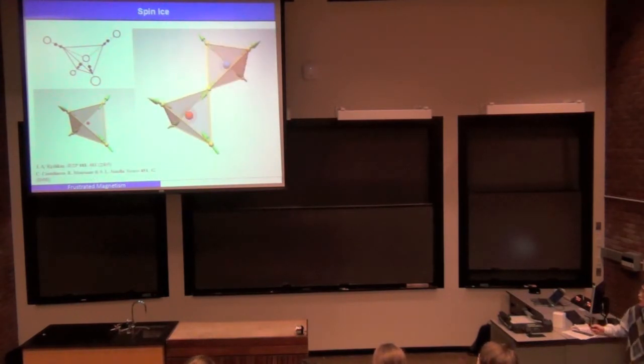And later people realized that when you have these so-called ice rules to enforce the two-in, two-out structure, if you flip a single spin out of the ground state, for example, if we flip this spin here, then for this tetrahedron you have three out and one in. But for this one you have three spins pointing in and one spin pointing out. So effectively for those two tetrahedra, the magnetic charge is unbalanced. And the result is the same as creating a pair of magnetic monopole and anti-monopole in those two neighboring tetrahedra. And this is an interesting realization of novel particles that cannot be found anywhere else, but can be realized in a condensed matter system.